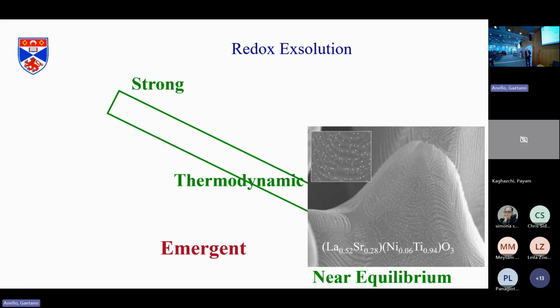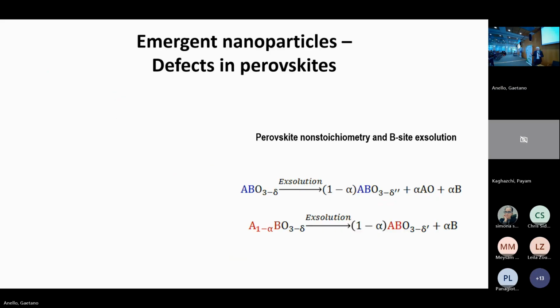You get this very fine structure, 15 nanometer particles, 10, 20 nanometers apart. So really almost breaking the laws of physics and chemistry. You'd expect Ostwald ripening here. So the trick that we do is often we have A-site deficiency. So rather than forming three phases on exsolution, you produce your metal and you form a perovskite that's closer to pure perovskite. So you start with an A-site deficient perovskite.